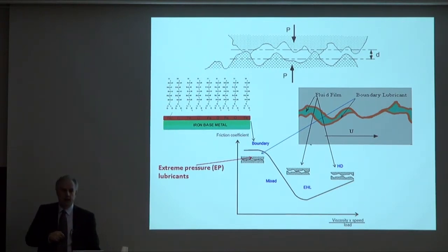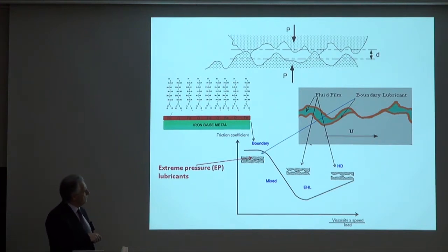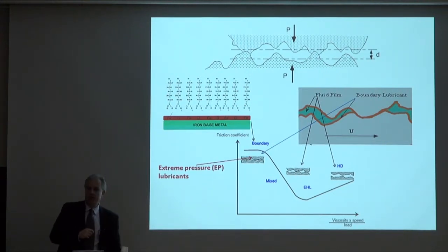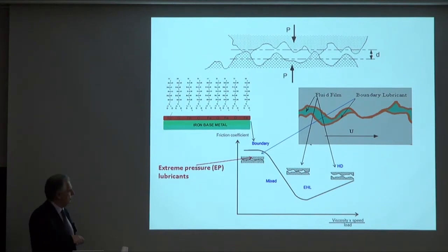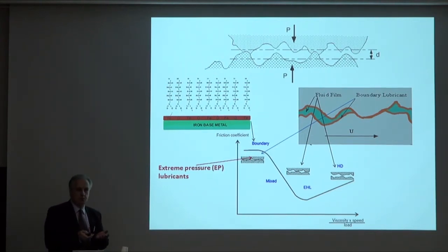So it undergoes a higher pressure, which now begins to deform those asperities that, although they may not be in direct contact yet, see a high pressure and undergo elastic deformation. And so elasto comes from the fact that the surfaces cannot be treated as rigid as here, but here they're elastically deforming. Still, though, it's a hydrodynamic film, and you can experience lower friction than here because the thickness or the volume of the sheared material has been reduced from here to here. Also, the shear rate has been reduced because now I'm moving slower. So both of these effects will explain why there is a slight trend in the friction coefficient.